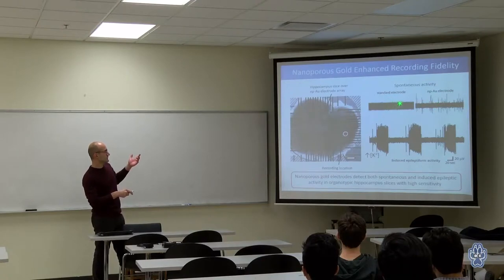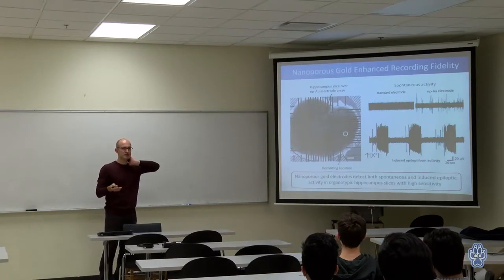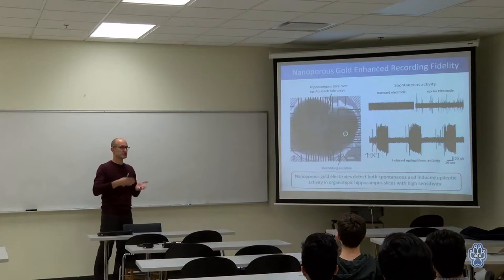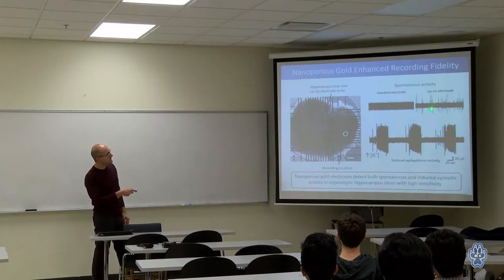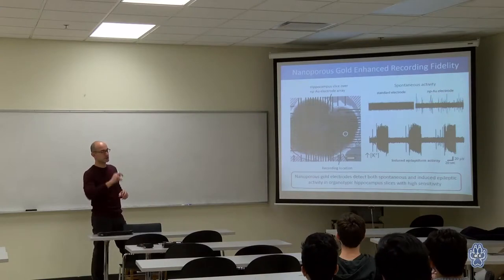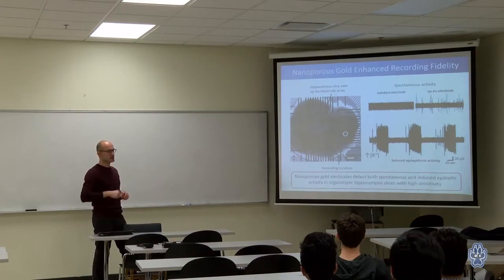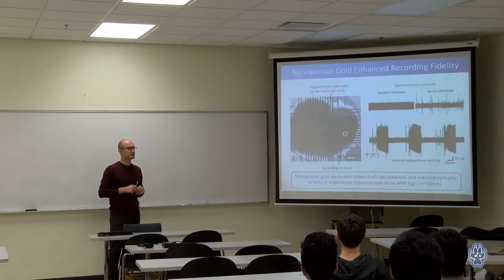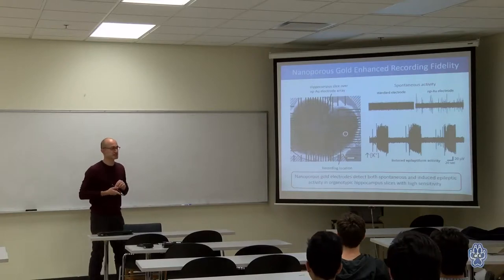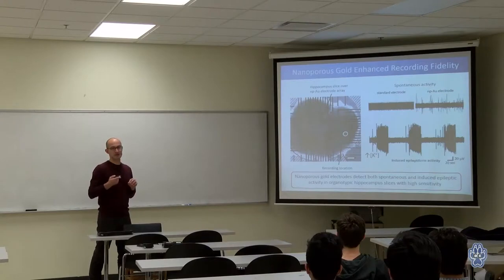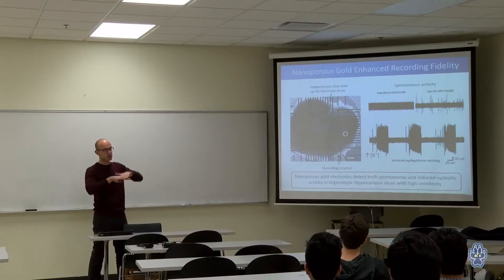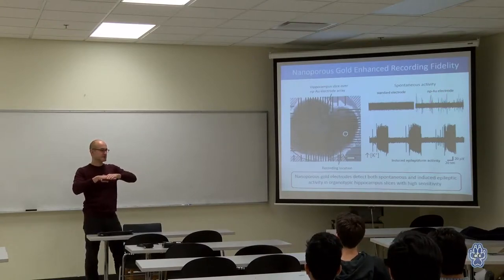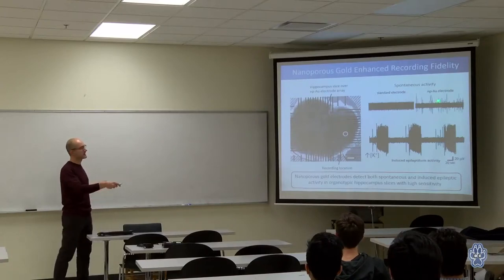The first thing you notice is that you reduce the noise floor when you go to the porous gold. And this is really due to the lowered impedance. You now match those voltage changes a little bit better in the electrode. But then you also begin to reveal more signal, if you will. So we reduce the noise, but there is actually a higher signal. Any thoughts on why there could be higher signal? What is actually generating the signal? Neurons, right? Neurons are pumping these ions, and they are the signal generators. So these neurons should be closer to the electrode, as I described before, the transmitter-receiver problem, hence we are seeing a higher signal here.